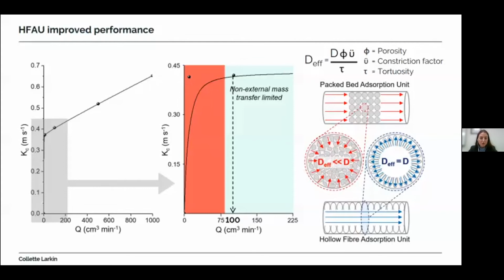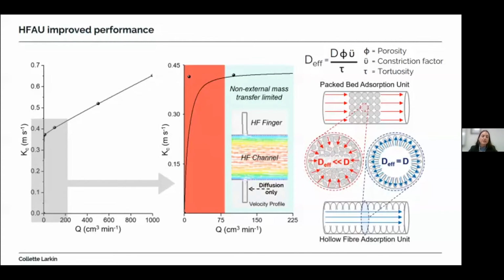However, in a hollow fibre adsorption unit, the CO2 flowed through the empty channel before diffusing into the open microchannels of the finger-like region. As shown by this snapshot of a velocity profile for the flow of CO2 inside the fingers, we know the CO2 enters the fingers by diffusion only. Thus, for the hollow fibre adsorption unit, the internal diffusion is governed by the opening of the fingers, which possess a porosity, tortuosity, and constriction factor equal to 1. Therefore, for a hollow fibre adsorption unit, the bulk diffusion coefficient is approximately equal to the effective diffusion coefficient.